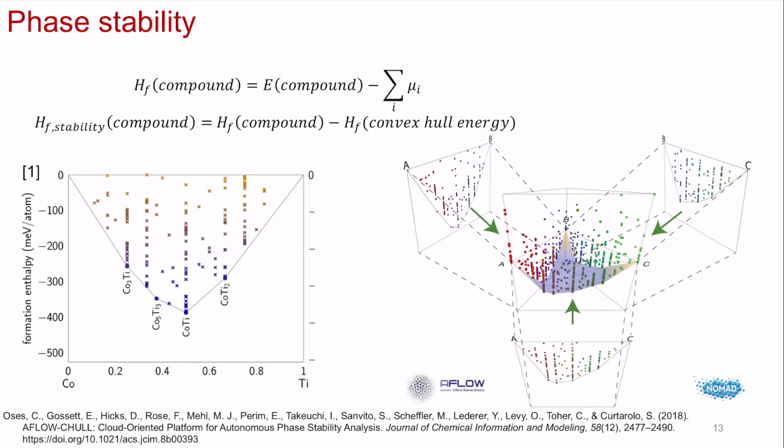So you can run DFT calculations and say, okay, at certain compositions and mixing, what is the energetically stable phase? So that's the lowest point. Okay, I should do it on here, sorry. What's the lowest point on this energy curve? So the formation energy of just the element is going to be 0 by definition, right? Single atoms don't form themselves, so by definition it's 0. Anything below that, the more negative, the lower the values, the more energetically favorable.